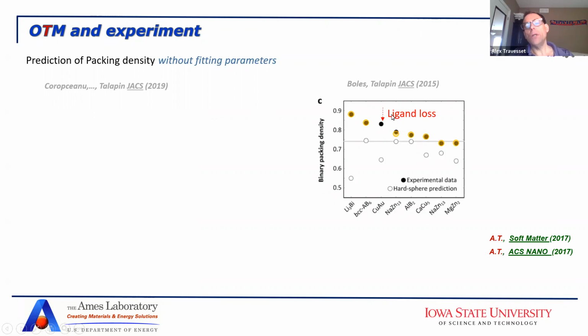And they immediately told me, oh yes, we know. What happens here is that for this lattice, this happens for lead sulfide nanoparticles where the ligands are very softly attached, and then under washing it many times, we lose them. So then this corresponds to a different type of assembly, which is not driven by the ligands, but is driven by the actual washing and the fact that the nanoparticles move face to face. So that was a big success of the prediction in the sense that I could predict all these ones except that one. That one happened to have a different effect. There is a paper that they published later about how this happens.